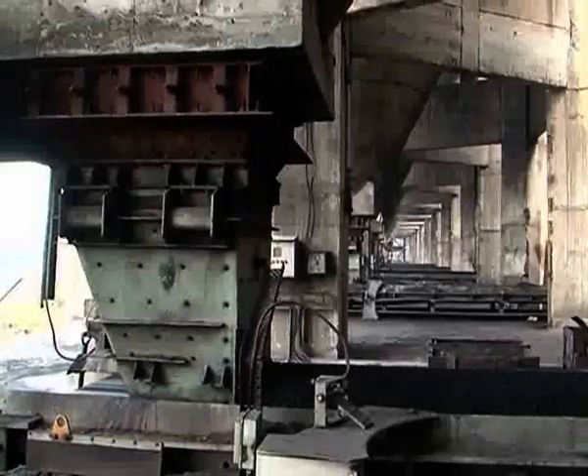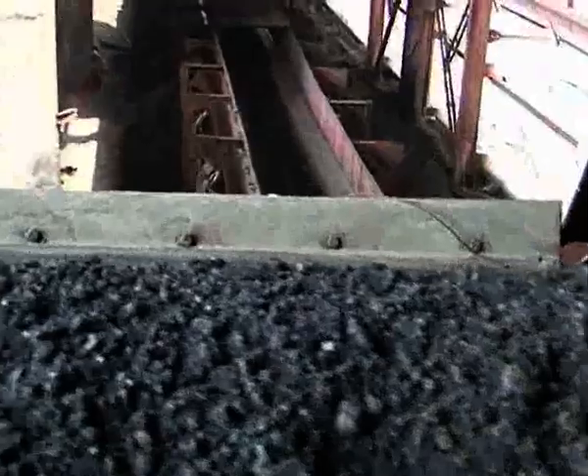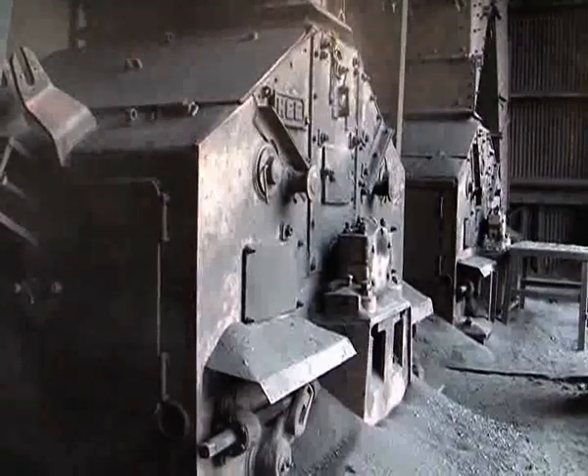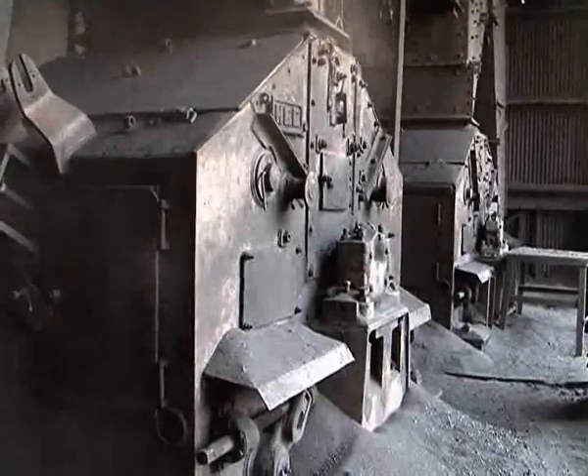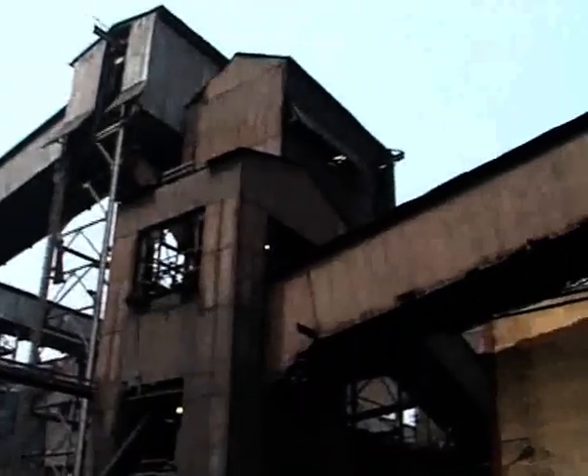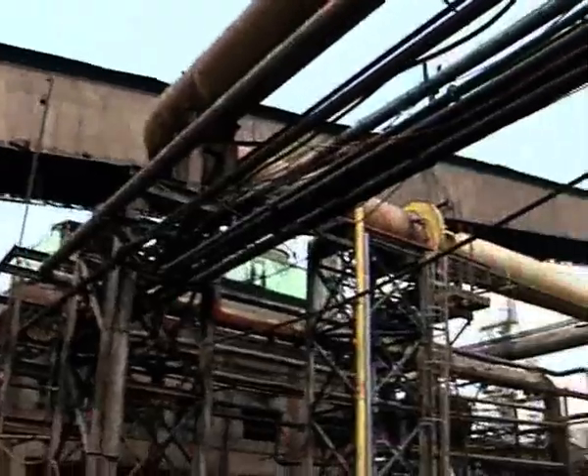Coal from the silos blended at the wave feeders is sent to the crushers. There are 4 numbers of crushers. The crushing is done in such a manner so as to ensure a maximum of 82% coal feed being of size less than 3.12 millimeter. The total coal feed is sent to the battery coal bunker through conveyor belts.